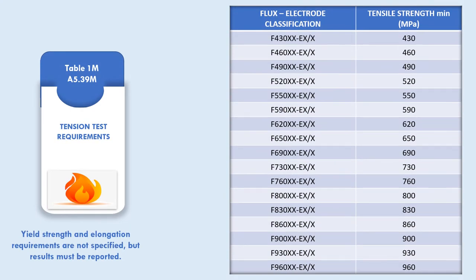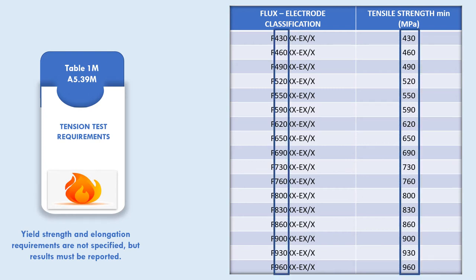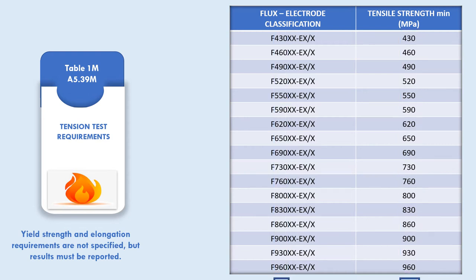Table 1 gives details about the tension test requirements. 'F' is followed by a three-digit number; that three-digit number indicates the tensile strength requirement. For example, the number 430 indicates that it meets the tensile strength requirement of 430 MPa. Weld metal from a specific flux-electrode combination that meets a higher tensile strength requirement also meets the requirements of all lower strength designators in the table.